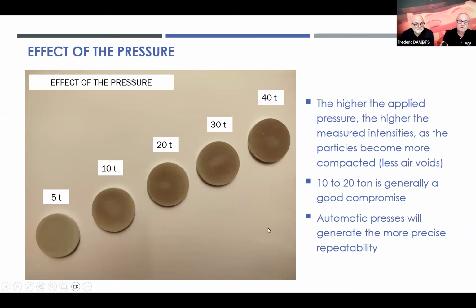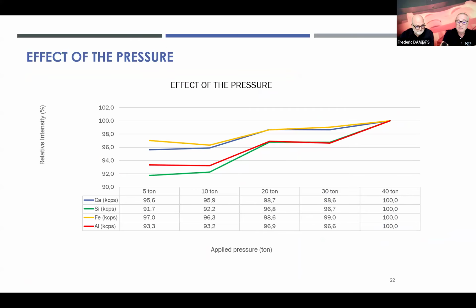Yeah, so of course, when we use an automatic press, we may generate more precise repeatability. We can see the effect of the pressure. Well, yeah, again, here the 4 elements, calcium, silicon, iron, and aluminium. We can see again, iron is less problematic. We go from more or less 97% of relative intensity to 100%.